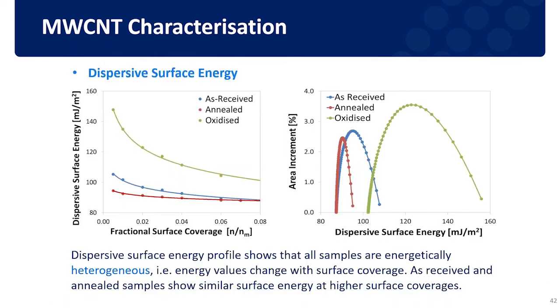So we measure the surface energy of each of the three individual components by filling the column of the IGC with about 10 milligrams of the sample, and then we perform the experiment at 100 degrees with a preconditioning at 120 degrees for 2 hours. The dispersive contribution of the surface energy dominated compared to the specific, due to the carbon-carbon interaction, and the combination of the high dispersive surface energy and high surface area given by the sample gives very high affinity with the organic vapor. That's why we need to apply very high temperature for those kinds of elution times of organic vapors.